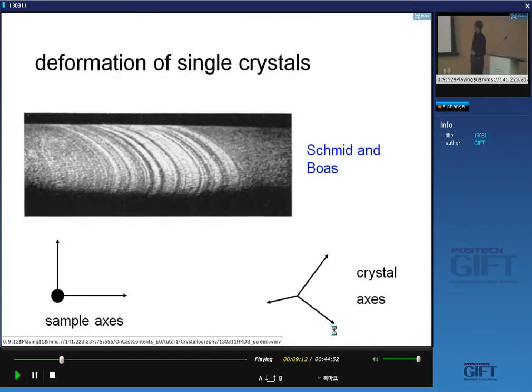Now, this is a classic piece of work, the original work on the deformation of single crystals done by Schmid and Boas. You can download their entire book from my website. It's a classic book on crystal plasticity. So basically, you take a crystal and you stress it. Now, supposing there are 24 possible slip systems. How can I decide which slip system is going to operate? So for example, a cubic crystal like ferrite or austenite will slip on 111 planes in the 101 directions. And if you look at all those slip systems, there'll be 24 possible slip systems. So how can I decide which one is going to operate? Which one or more are going to operate? Yeah. Any ideas?